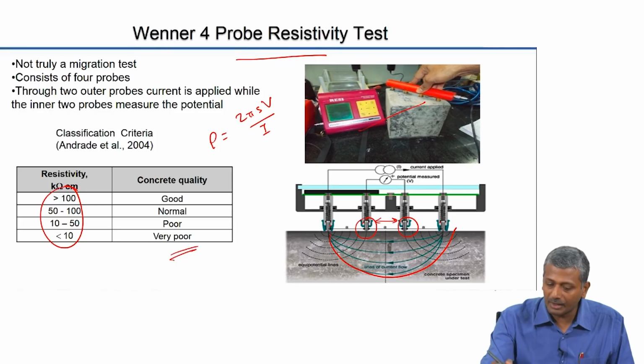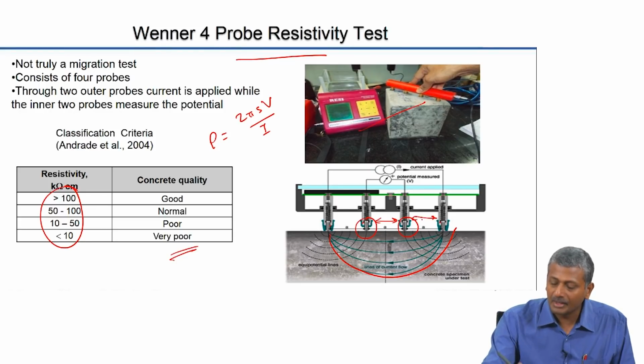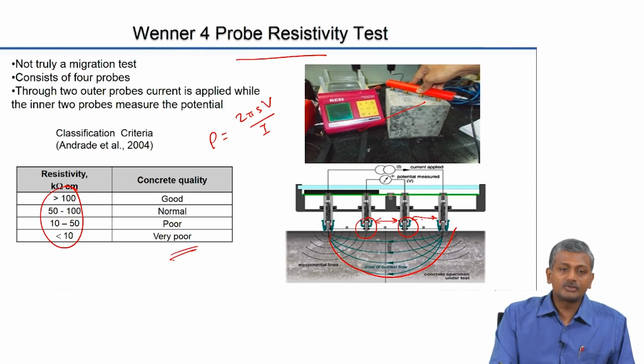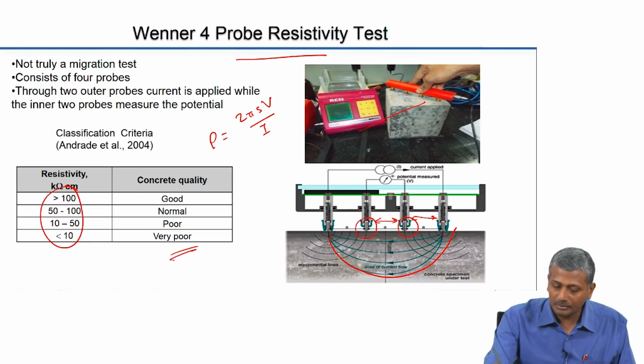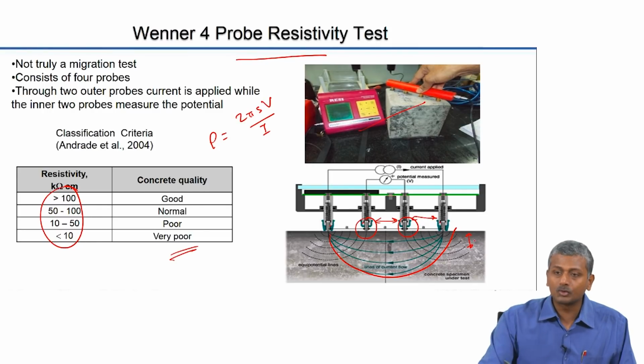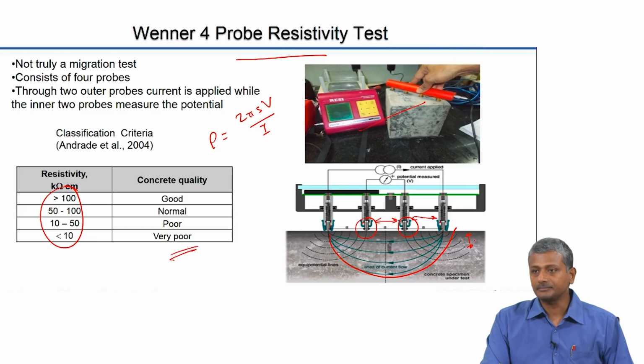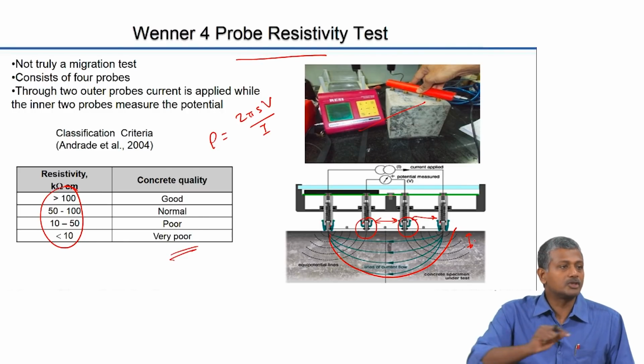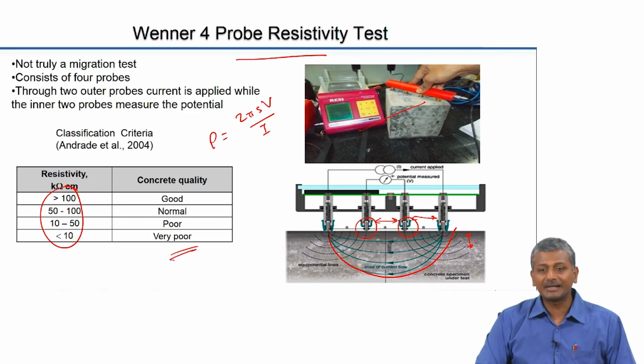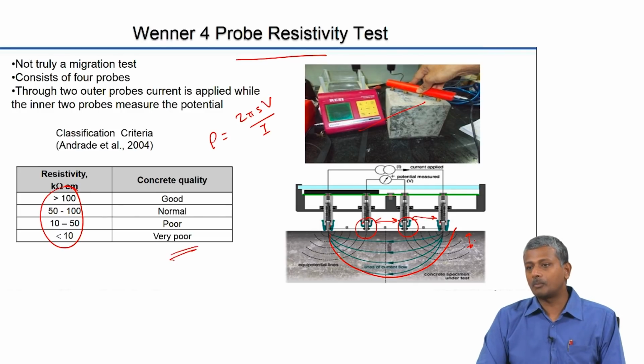So, for that what you will have to ensure is the spacing between the electrodes is small enough so that your current lines are flowing only through the cover zone of the concrete. If you use a small spacing, you ensure that the current lines are only flowing through the cover zone of the concrete. In that case, you are actually measuring the property of the cover zone itself. Otherwise, you will have the steel also coming into the system.